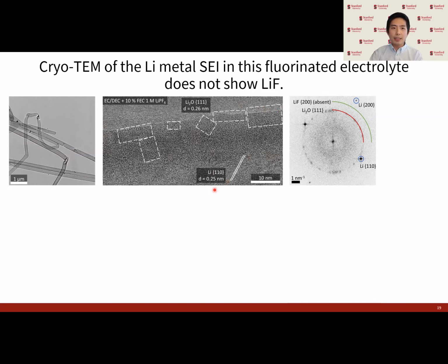We can see lithium metal down here, and what we're mostly seeing are amorphous organic materials along with lithium oxides in the SEI. This Fourier transform converts all the spatial information here into frequency information. So all these spots correspond to lattice spacings in the image. And we can see that there's a variety of different lithium oxide orientations, but no lithium fluoride as well. But this mode of TEM imaging is highly sensitive to crystallinity. So if lithium fluoride were in principle amorphous, we would not be seeing that.